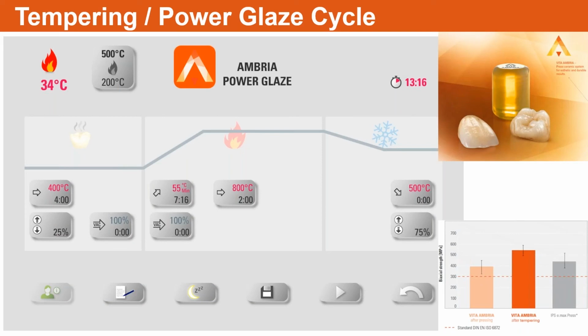As far as that power glaze, it's a 13-minute cycle. I know it's an additional cycle, but this really dramatically increases the strength, brings it up above the 550 megapascal flexural strength level. So make sure you do that. It should just be routine, and then you don't have to worry about it.